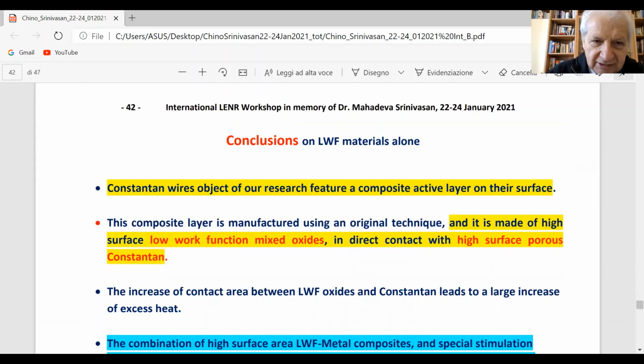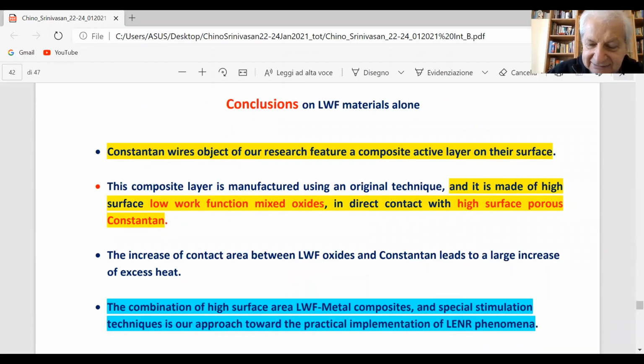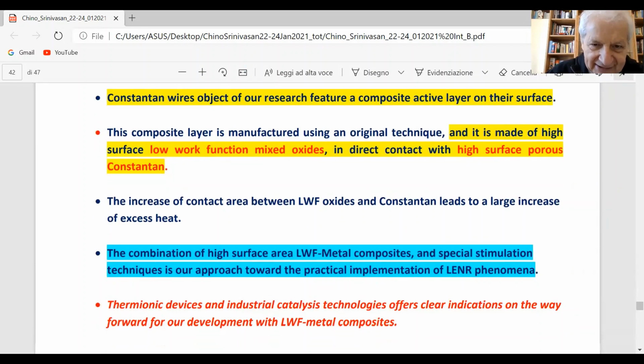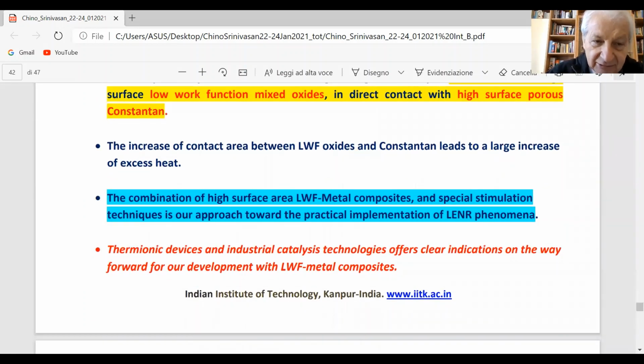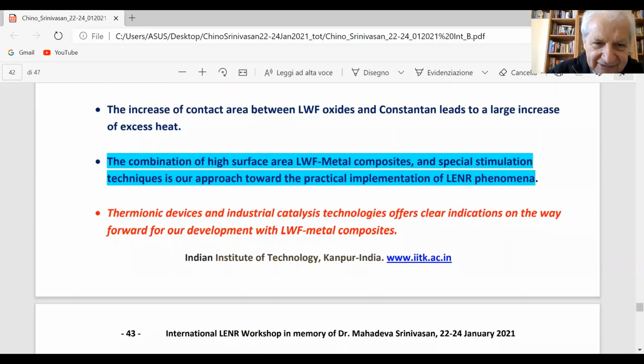Conclusion on low working function. Constantan was an object of our research, adding a layer of low working function material, and the contact has to be as close as possible. So the combination of high surface area with low working function materials is a special favorable condition to have anomalous heat effects.